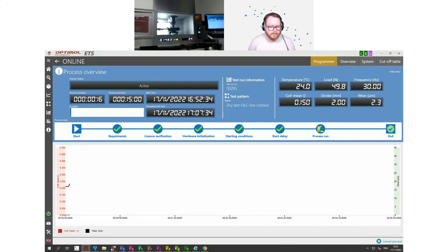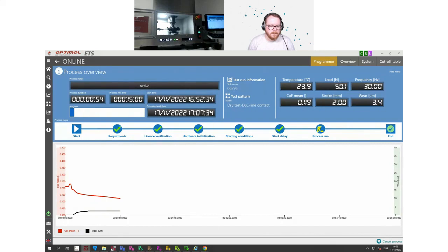And what is very interesting with this coating that we are testing here at the moment, that if you remember our reference with 1 micrometer of wear over the entire test, this coating immediately increased to 2 micrometers. So already after 1 minute of test, the wear is relatively higher than the reference. And with that, you could save time and immediately stop the test, because this sample here is already disqualified. Its performance is worse than the performance of the reference.